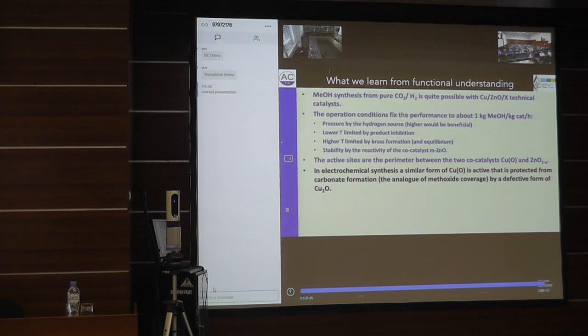We also tested, of course, the electrochemical synthesis of methanol from copper under the CO2 reduction in the electrochemical cell. And of course, that also works. It has a different kind of limitation. The limitation there is carbonate formation. That is the analog of what is in the gas phase, the methoxide formation. And there's also a defective copper oxide as the active phase, and the recrystallization under electrochemical potential of the defective copper oxide into perfect copper oxide is the deactivation mechanism of the electrode. So that is rather similar.